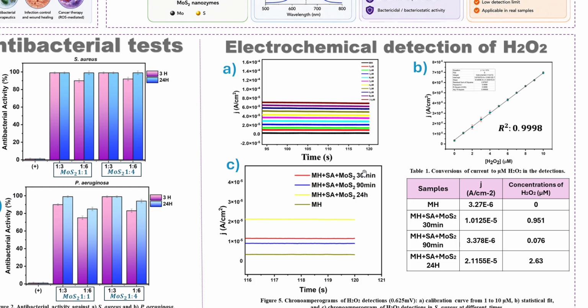Another important part of this work was the electrochemical detection of hydrogen peroxide. We used a three-electrode system with a platinum working electrode. First, we obtained the calibration curve for hydrogen peroxide in the micromolar range. As shown here, a very good linear relationship was obtained between hydrogen peroxide concentration and electrochemical response, with an R squared value of approximately 0.9998.